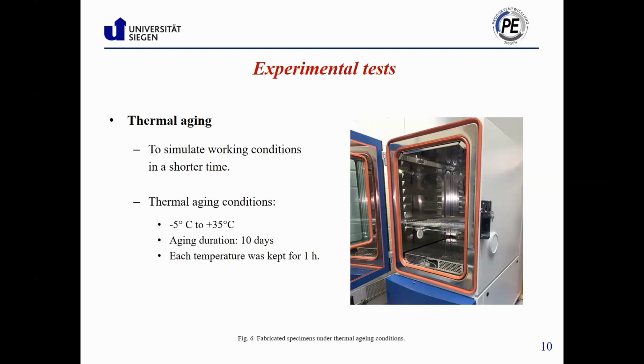we used an environmental climate test chamber, and the specimens were artificially aged in the temperature range of -5 to +35 °C. Each temperature was kept for 1 hour, and aging duration was 10 days. In this figure, you can see specimens inside the test chamber.